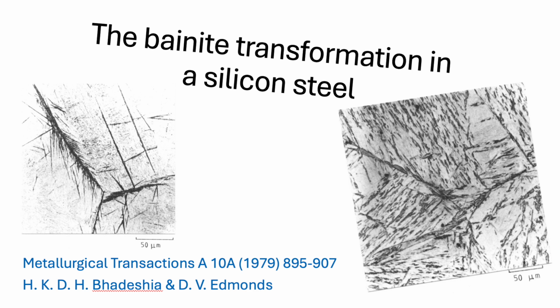All right, let's unpack that. For listeners maybe not deep into metallurgy, why add so much silicon? What's its role? Silicon is well known for strongly inhibiting the formation of cementite, that's iron carbide, Fe3C. Right, the hard stuff in steel. Exactly. And in most steels, when bainite forms, carbides tend to precipitate out almost immediately, either between the ferrite plates or inside them. Which messes up the observations. Totally. It removes carbon from the picture right away and makes it incredibly hard to figure out the fundamental mechanism of how the ferrite itself is forming. Is the carbon leaving during formation or after?